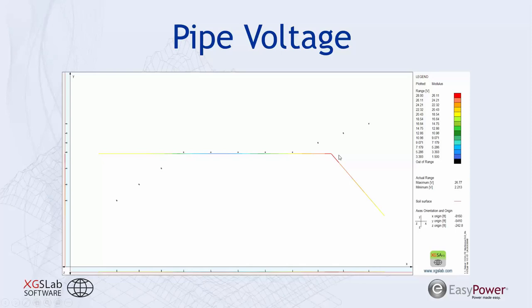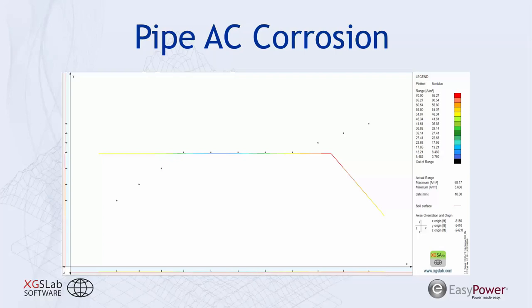And this is a steady state issue, which is going to be present anytime that the transmission line is operating. So when the pipeline personnel are performing their routine tasks like opening valves or checking test leads, they could be subjected to a hazardous voltage at any point. Similarly, we have sufficient induction on this pipeline that we would expect this pipeline to corrode at an accelerated rate because of that AC corrosion phenomenon we talked about earlier. And this sort of sets up our base case for the steady state analysis that I'm going to look at. And we're going to try a couple different mitigation approaches and just compare and contrast how those work.